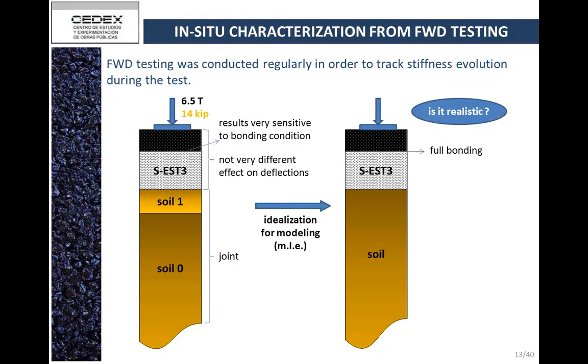Now, in order to see the evolution of the stiffness of this material, we conducted FWD testing periodically during the test. One of the concerns is related to conducting FWD back calculation in this type of section. In the first place, back calculation would be unable to distinguish between this small layer. This is a soil, and this is another soil. This soil 1 is slightly better than soil 0, but in practice we didn't try to obtain the modulus of the soil 1 layer. We obtained a modulus for the combination of these 2 soils. So this was the first thing, which probably was not a very important simplification.